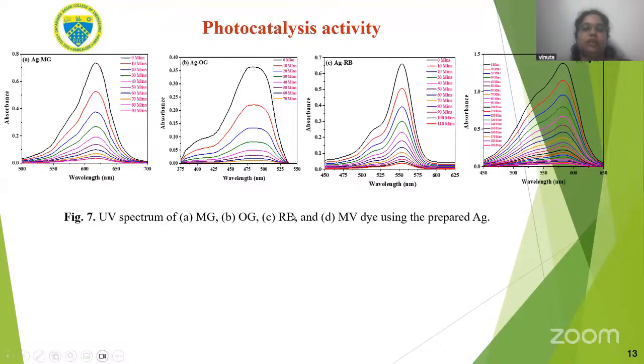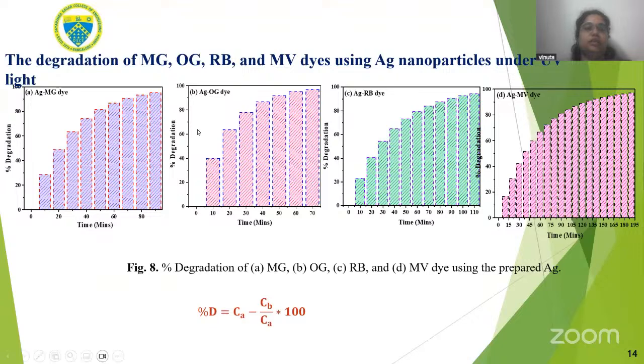So this is the photocatalytic activity of the silver nanoparticle with the various dyes. This is the degradation of malachite green, orange G, rhodamine B, and methyl violet dyes using silver nanoparticles under UV light. Here we have maintained the same concentration and same volume to compare the activity against the various dyes. So almost for all the dyes, the activity was similar.